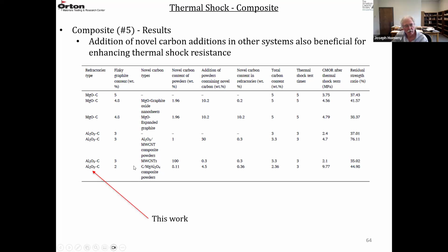But the last one here is the one we just looked at, the aluminum oxide carbon composite with these graphene spinel powders, and the residual strength was about 45%. So in some cases, nanoparticle additions, depending on what they are, have actually improved the thermal shock resistance. So other people have researched this recently.